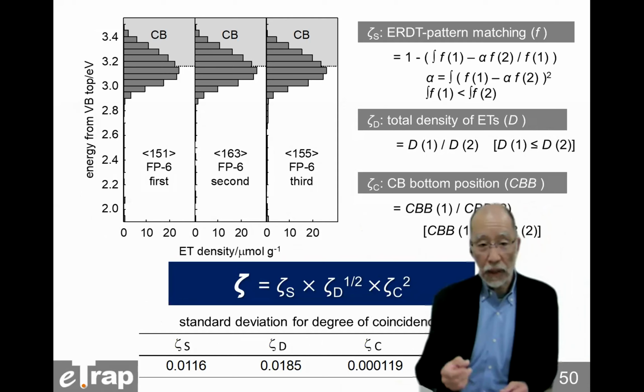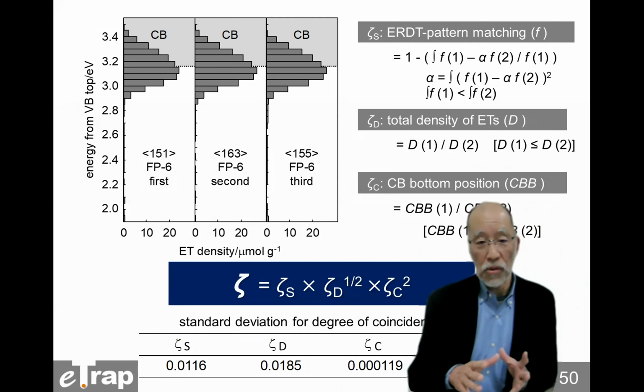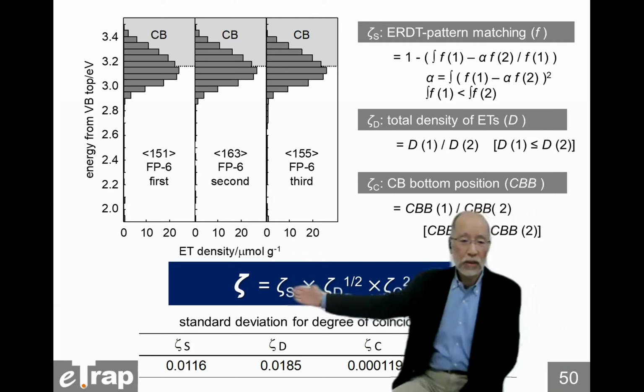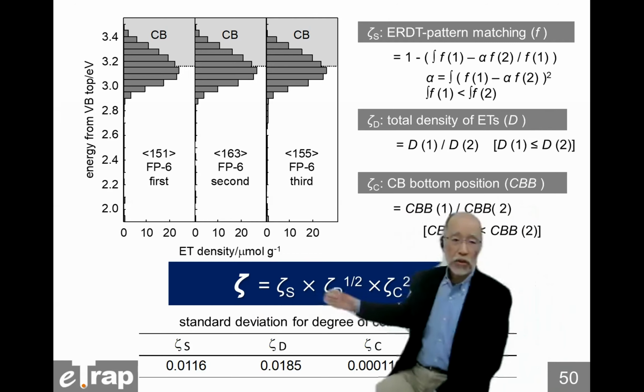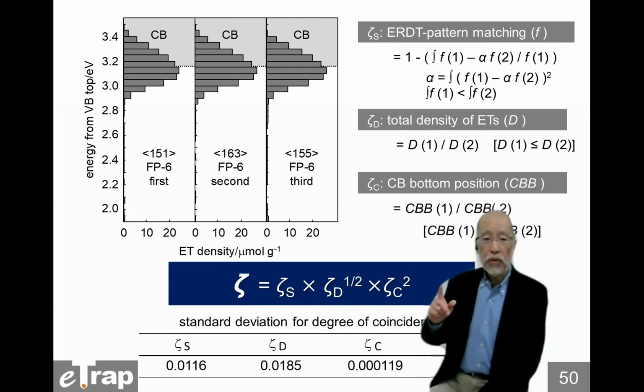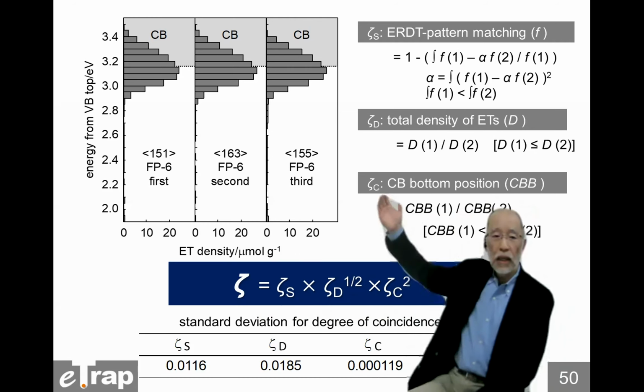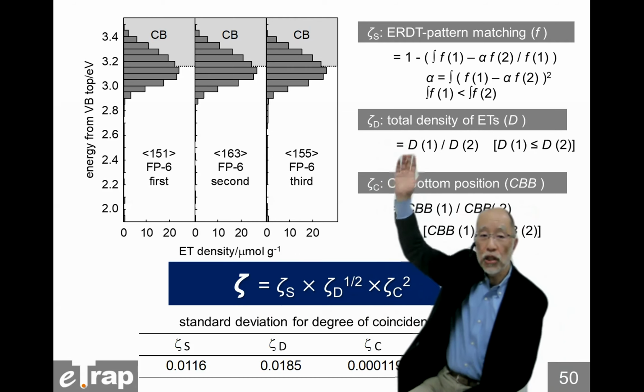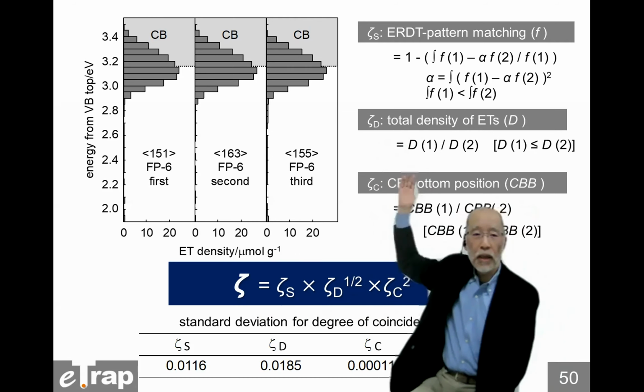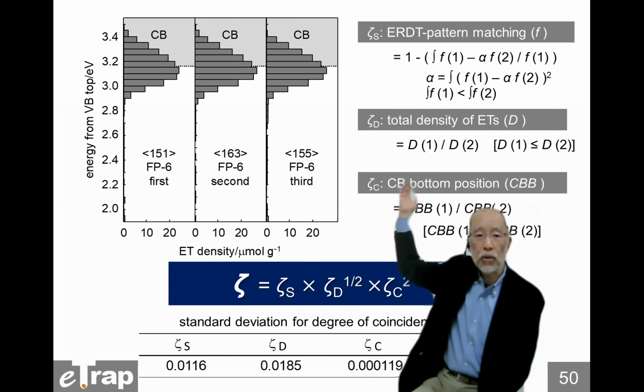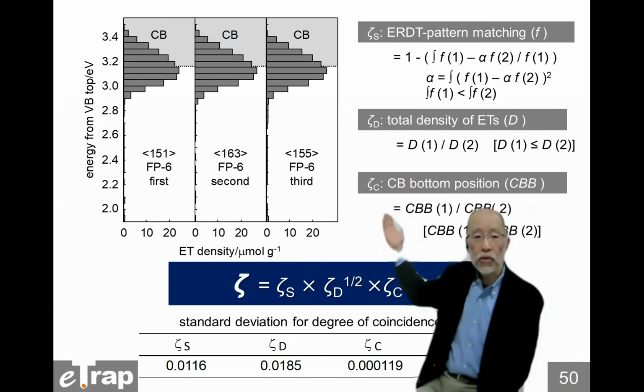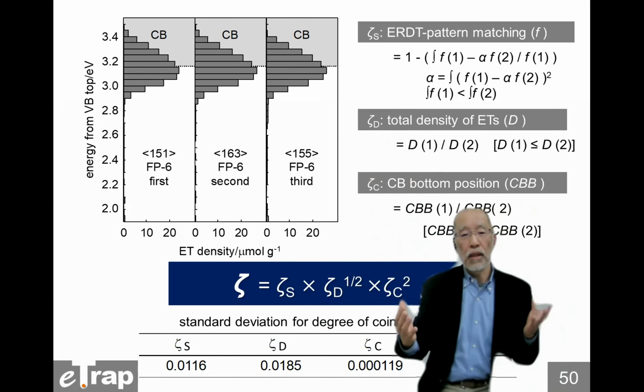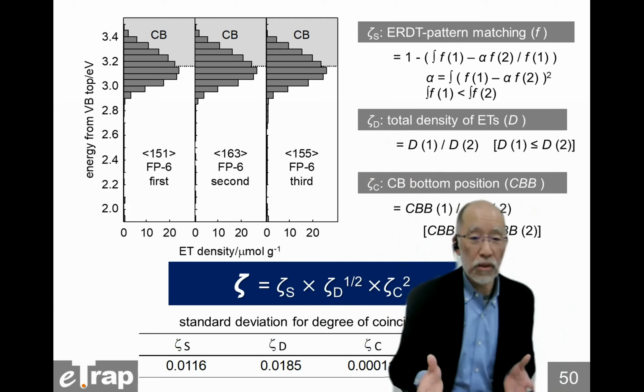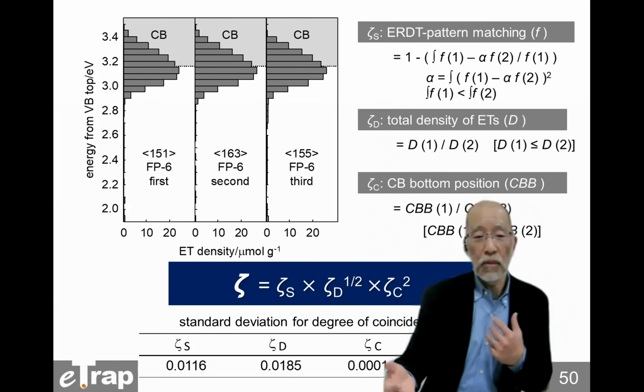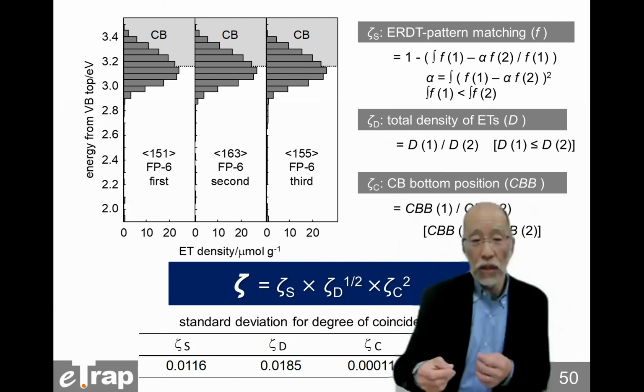And to check the similarity or identicalness of patterns, we introduced a new parameter, zeta. Zeta is the multiplication of three partial degrees of coincidence. One is the ERDT-pattern, the matching of shape. The second one is zeta D, the total density. And zeta C is the conduction band position. Each partial degree of coincidence is calculated to give a value between 1 and 0. 1 is completely the same, 0 is completely different.